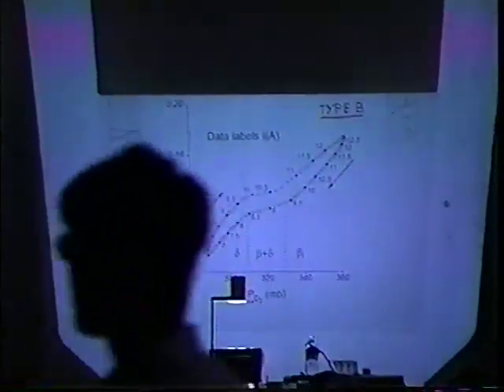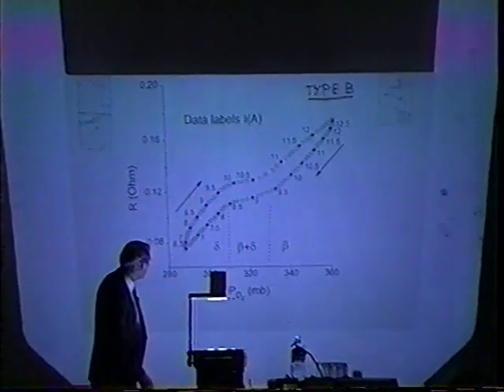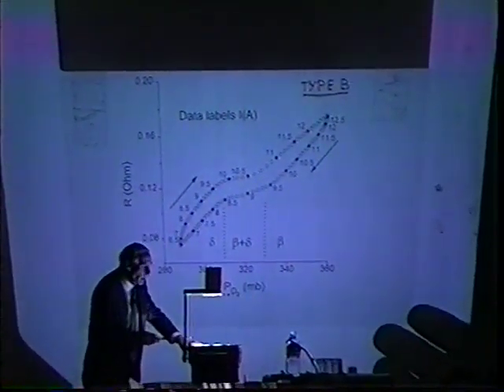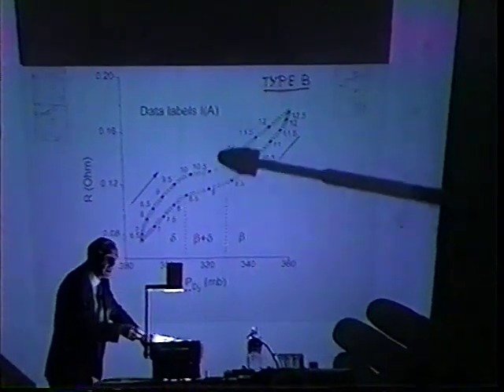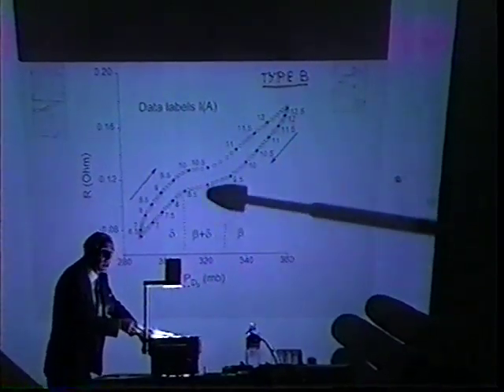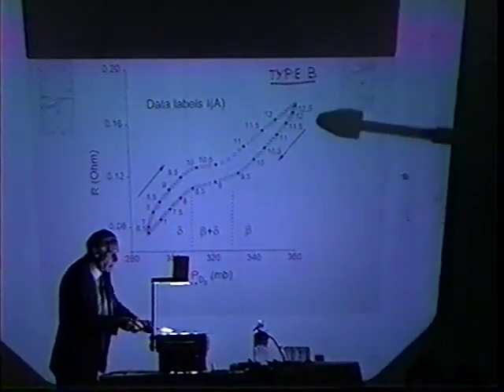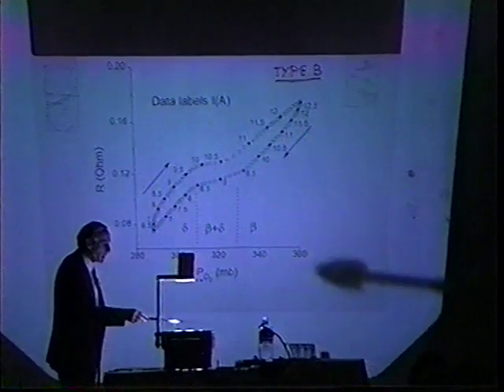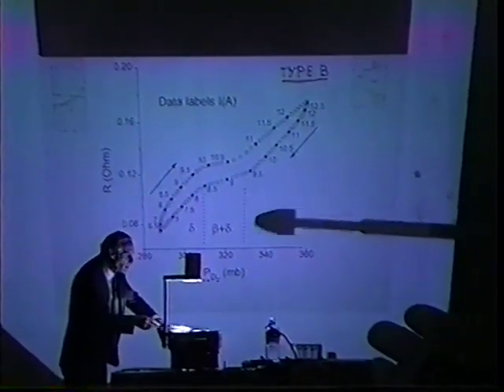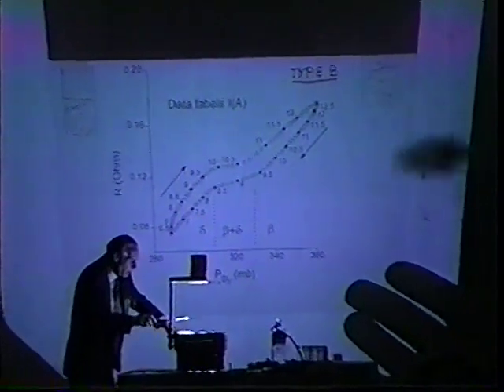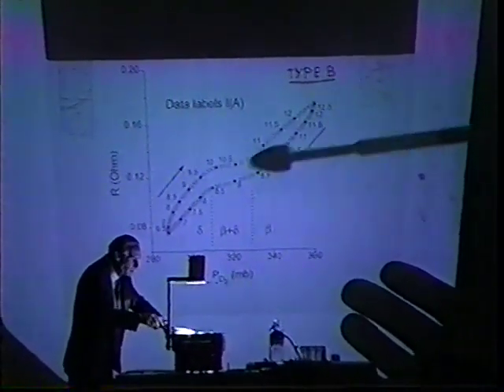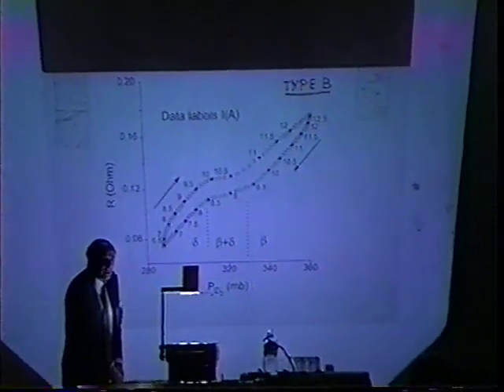The second type of experiments we have done is trying to see if phase changes in the sample are acting as triggering or stimulation processes. We have followed the phase changing by measuring the electrical resistance of the sample in situ during the process. This is a sample of the electrical resistance variation on passing from the beta to the delta phases. There is, as you can see, some hysteresis in the process. This is due mainly to the production of defects, dislocations, and small cracks.